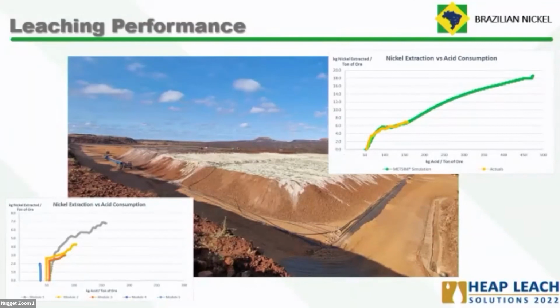The main reason why this is so good is because everything matches the model, the actual operation, the actual ore chemistry, and everything else match the model. So it's a good validation. Now the latest models, they start changing. So we start seeing different magnesium to nickel ratios that will have a consequence, and we will see curves that will, from the current model, go apart. I'm not presenting it here because they just have the 60 days, so it's not really very conclusive right now.